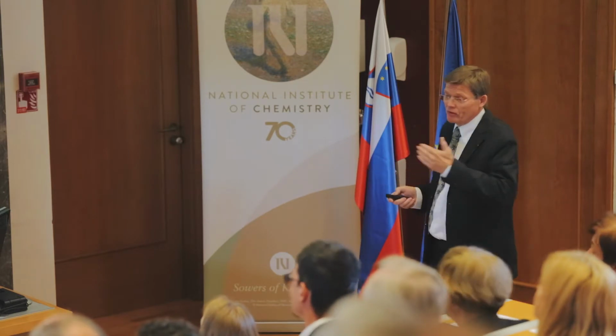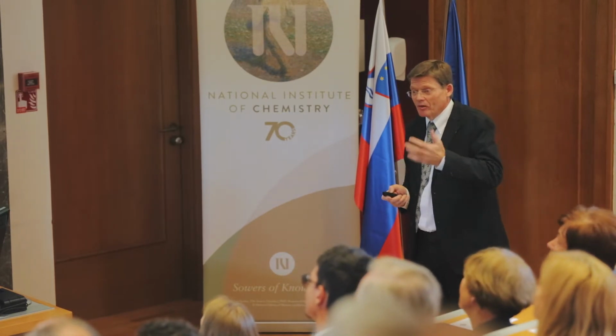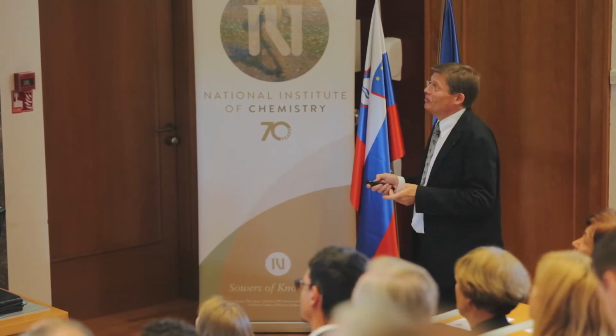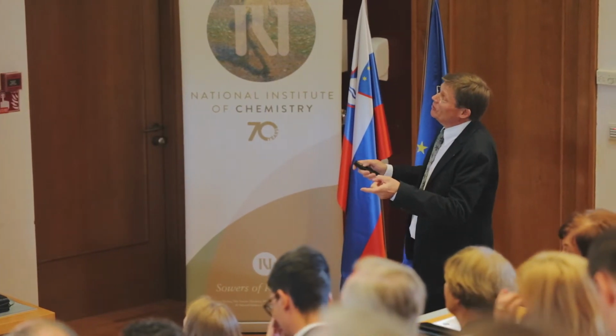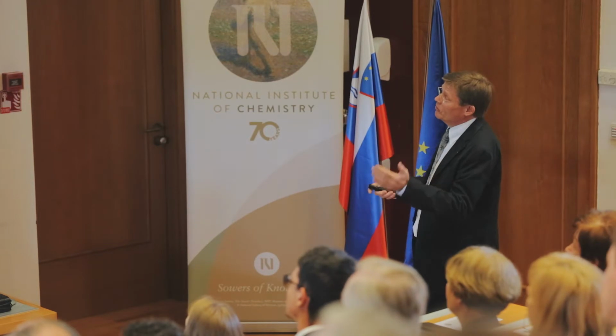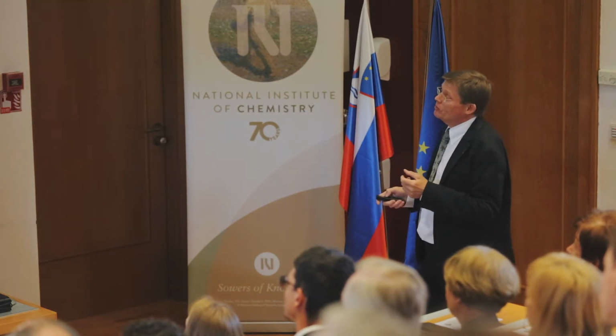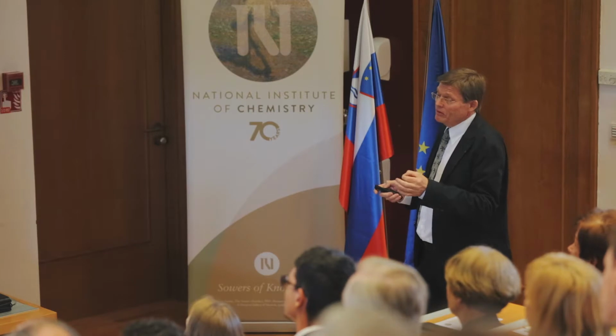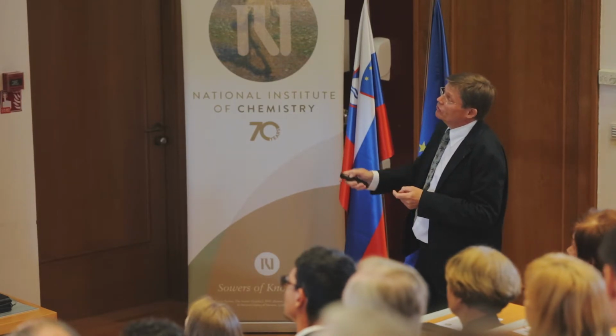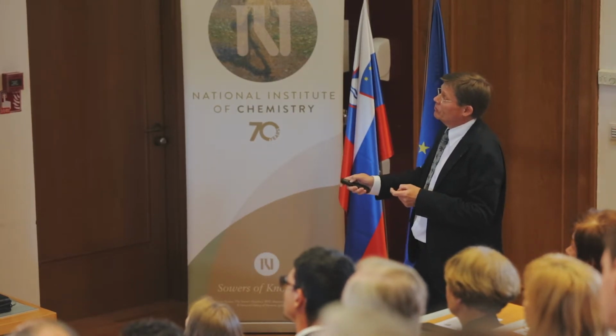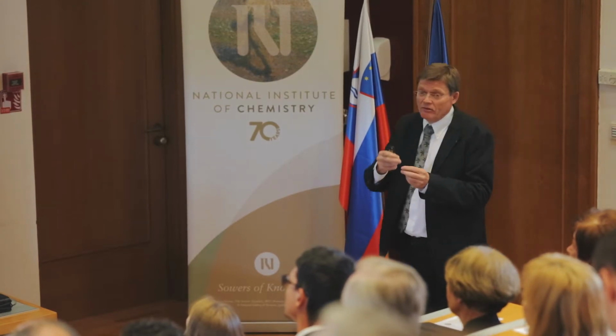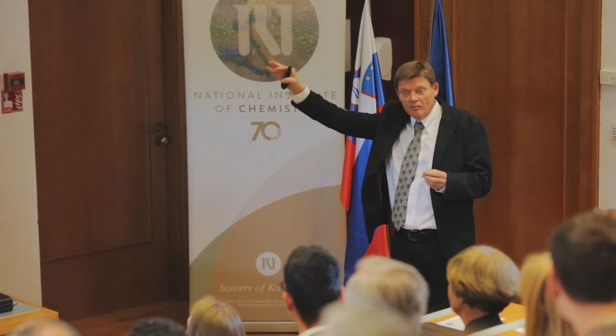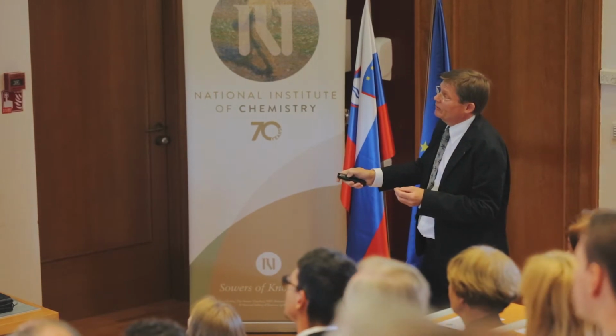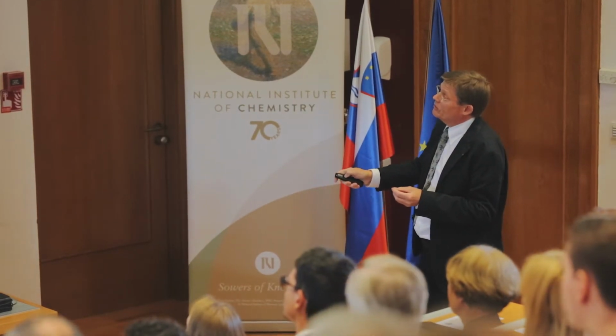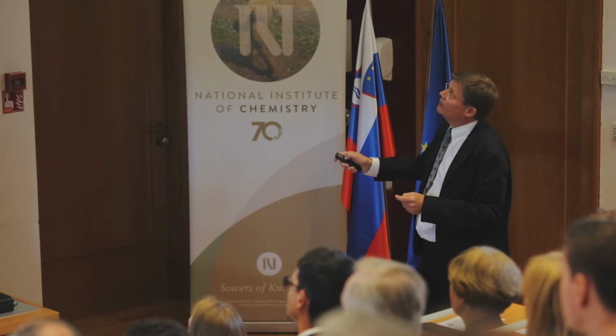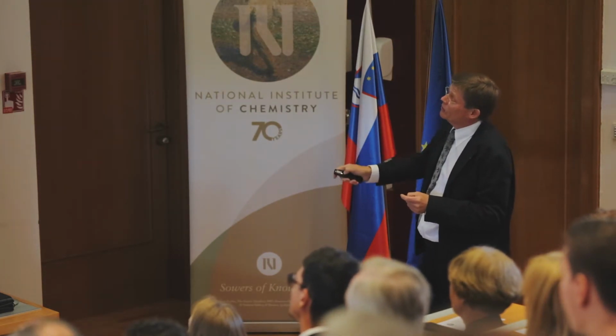You can do the same with frequency when you do impedance spectroscopy. Jan Sajnik was really a master of impedance spectroscopy. Now I have here the translation of that equivalent circuit in terms of frequency. These are the usual plots. You take the complex impedance, you plot the negative imaginary part versus the real part. And then for any RC circuit, you get a semicircle. This bulk, this interface, the grain boundary, and the interesting part, this stoichiometric polarization, is here.